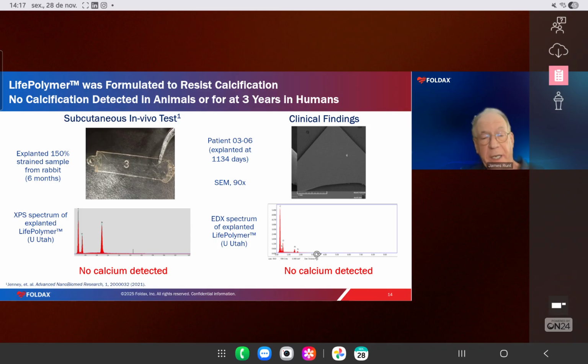Also from the clinic, after 3 years, this is an aortic valve, I believe. After 3 years of implant, we found, the top right is a not very high magnification scanning electron micrograph of the surface. It's pristine, just like the others that we've seen.